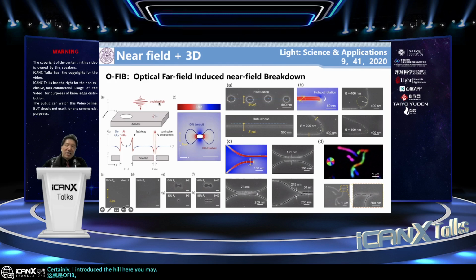You may ask, since the usage of the optical FIB depends on the creation of the seed, and the seed's shape and size are randomly produced, whether they will affect the fabrication. Actually, our answer is no. We found a self-regulation effect. Self-regulation means no matter whether the original seed hole size is larger or smaller, the resultant line width is not affected by the original seed shape and size.